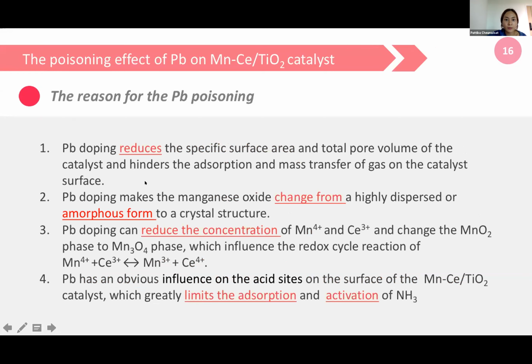The reasons for the Pb poisoning: 1. Pb doping reduces the specific surface area and total pore volume of the catalyst and hinders the adsorption and mass transfer of gas on the catalyst surface. 2. Pb doping makes the manganese oxide change from a highly dispersed or amorphous form to a crystal structure. 3. Pb doping can reduce the concentration of manganese and cerium, and change the manganese dioxide phase to the trimanganese tetraoxide phase, which influences the redox cycle reaction. 4. Pb has an obvious influence on the acid sites on the surface of the catalyst, which greatly limits the adsorption and activation of ammonia.